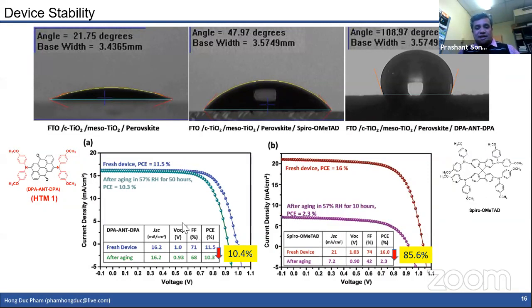And here is the device degradation mechanism, where we take a fresh device and age it at 57% relative humidity for 50 hours. Our power conversion efficiency drops from 11.5% to 10.3, whereas in the case of a Spiro-based device, it has gone all the way from 16 to 2.3. Very lousy, very immediate degradation. So this clearly gives an idea of how the contact angle of these STMs is important to enhance stability, and we get very significantly lower degradation, whereas in the case of Spiro, degradation is high, which might be obvious due to the low contact angle, as well as some of the ionic additives they use while fabricating the devices, which I mentioned, like lithium and those types of additives.